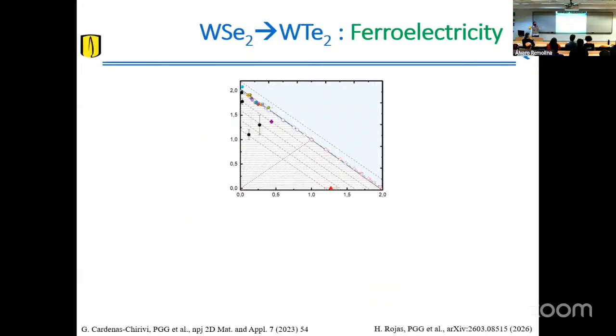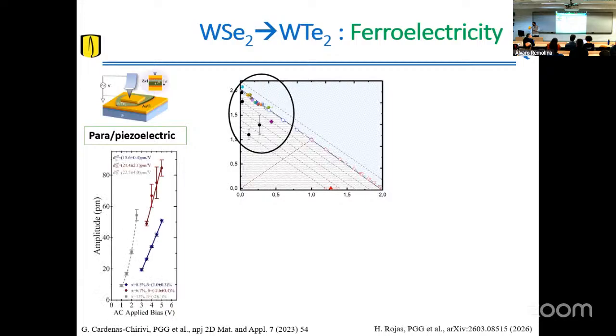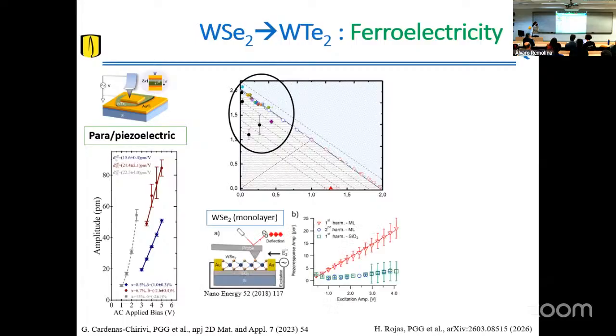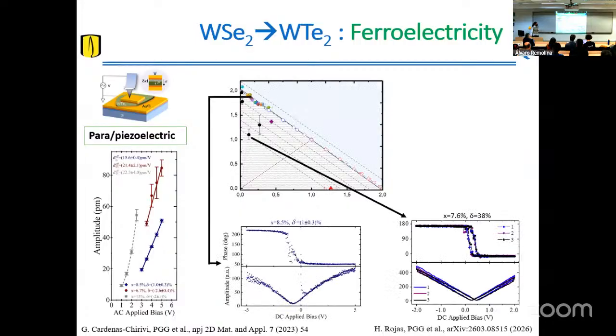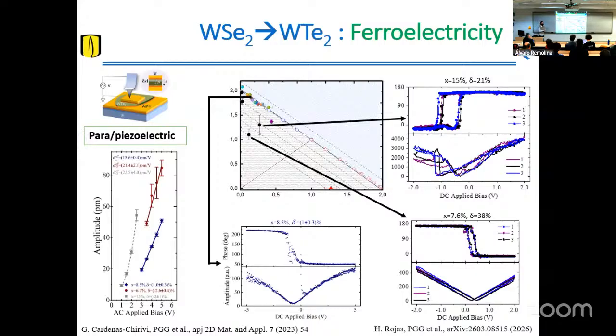We have done exactly the same for the ferroelectric order, and I'll go really, really fast here. So we have very good piezoelectric materials with piezoelectric coefficients that are comparable to commercial piezoelectrics like lithium niobate or others. So that's actually very nice, promoting these high values that are useful for engineering applications. And we have seen a beautiful hysteresis loop in these piezoelectric measurements that speaks of the ferroelectric order.